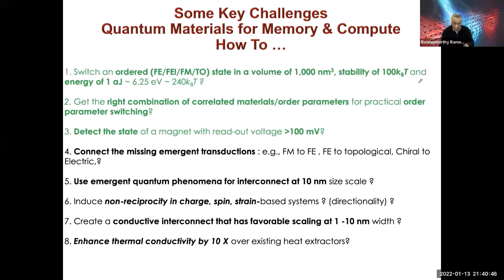In principle, we have done some measurements. Actually, Morgan, when he was here, he did those. He's never published those, or maybe he has, I don't know. He put magnetic dots of 100 nanometer kind of length scale within a single domain and looked at the switching of that. But we haven't done as much work as I would like to, because we want to make sure that we understand it well enough. And the stripe domains, when Morgan and John Heron did that beautiful piece of work, they used the stripes to establish that indeed there's coupling, because you can use imaging techniques like photoemission microscopy to show that the ferromagnet is coupled to the multiferroic.